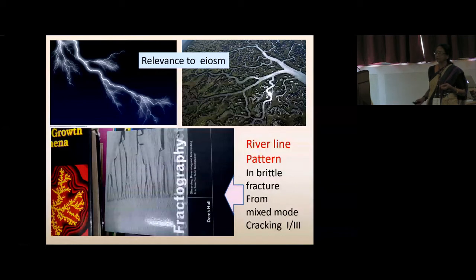It's called Fractography. And on the cover of the book, they have this nice crack pattern, which is called the river line pattern. This is brittle fracture, and it arises from a mechanical stress, not drying. But again, you have this very similar type of character. And it seems that nature has a sort of preference for systems to evolve in this way, in tree-like patterns, which are describable by fractals.